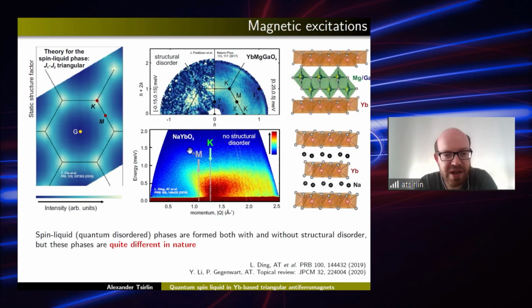So indeed, for the NaYbO2 compound, we have the intensity of the low energy excitations sitting at the position where theory expects it. So this was the strong evidence for the possible Dirac spin liquid state in this sodium ytterbium O2. On the other hand, we cannot really exclude the importance of just the pure two-dimensional order in these systems.